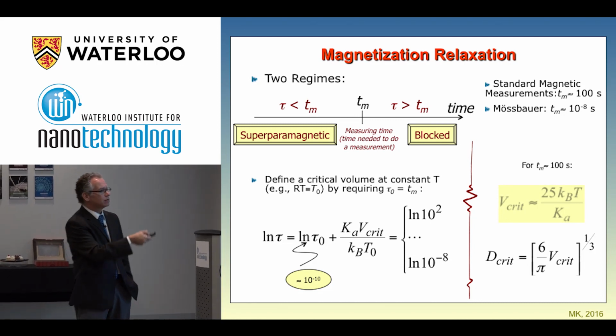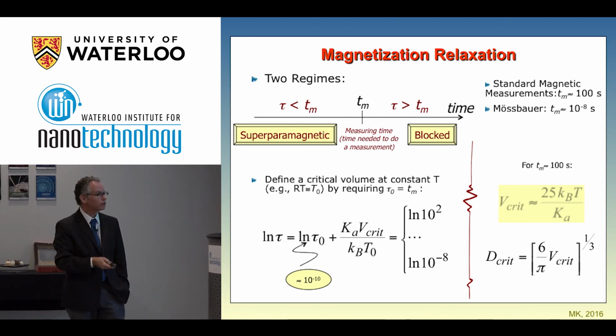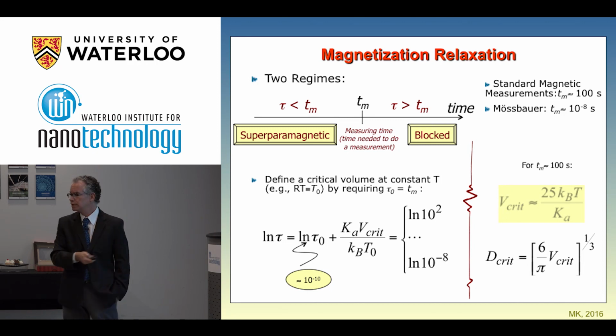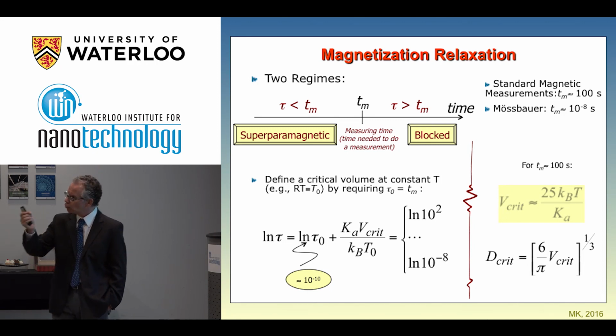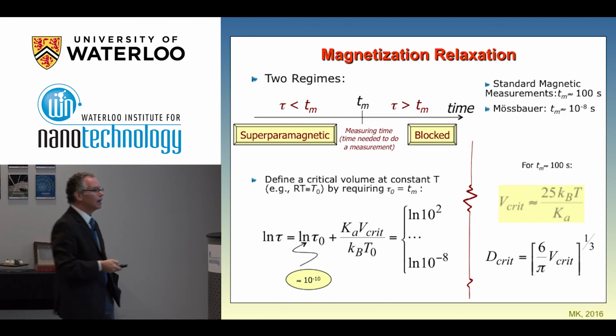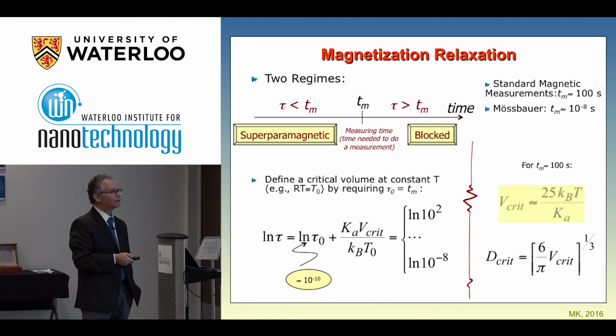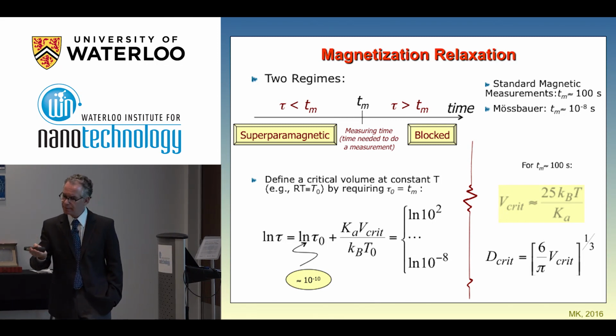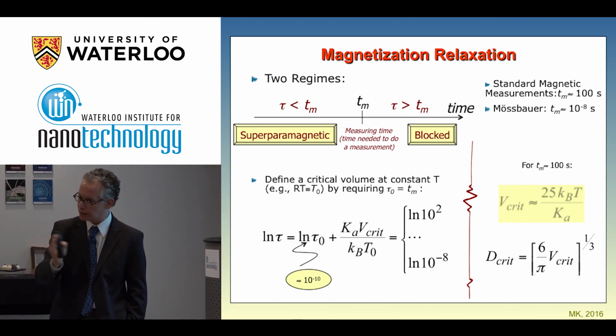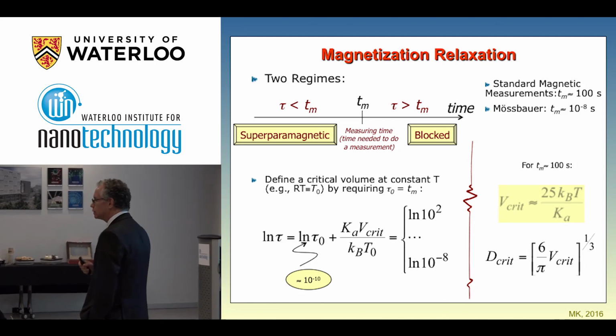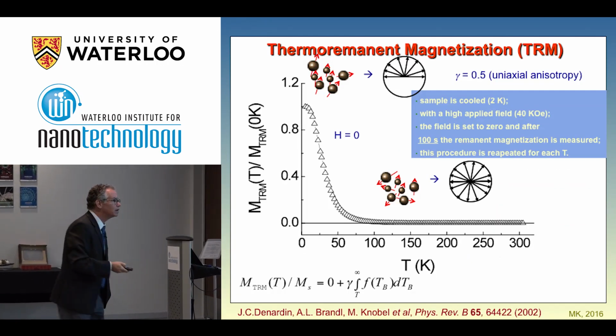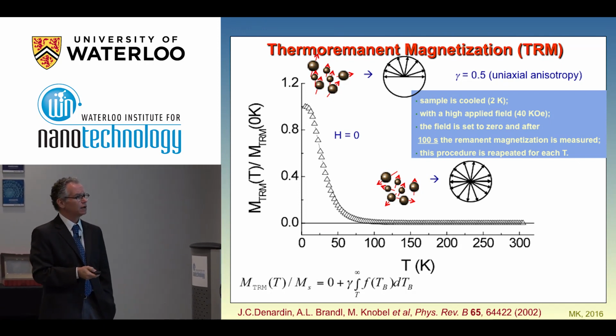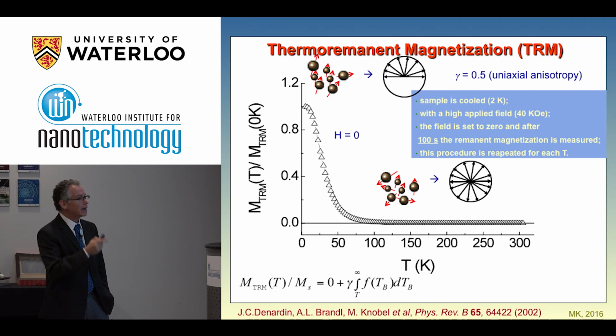And so you can go, I won't go into the detail, otherwise I won't have time. So usually in standard magnetic measurements, we consider 100 seconds. And if you make Mössbauer experiments, for example, you have 10 to the minus 8 seconds and so on. You can change your window where you analyze the system. And then you can calculate the blocking temperature where this happens. So the blocking temperature is the temperature where the system can go from superparamagnetic to blocked and so on. So I will skip a little bit of this physics or more technical part.